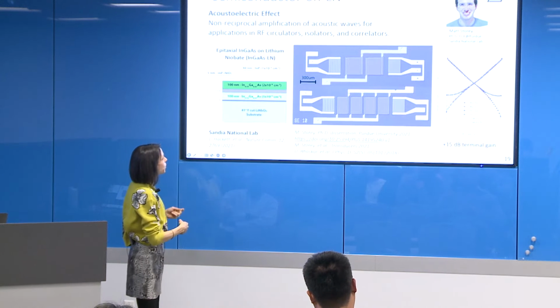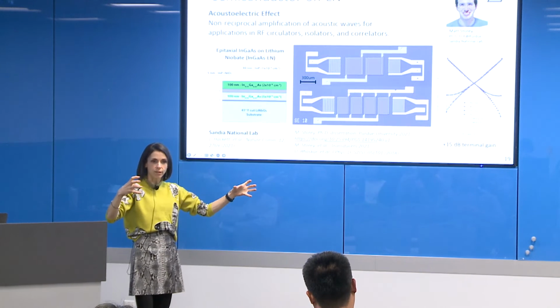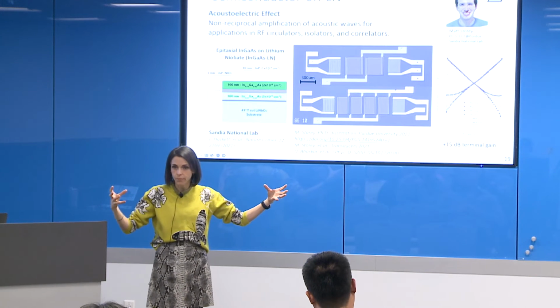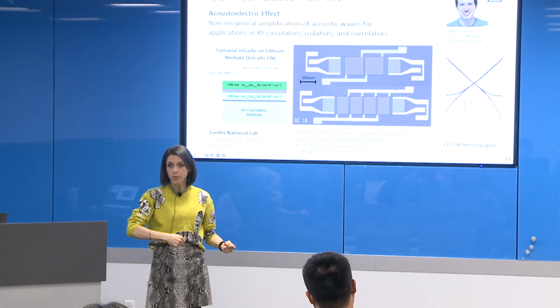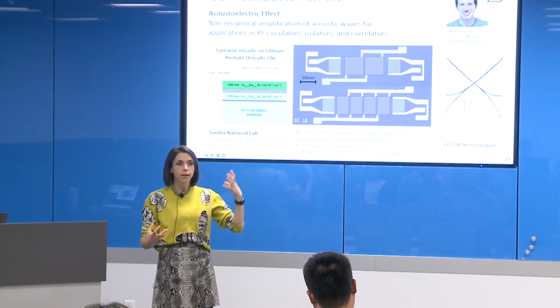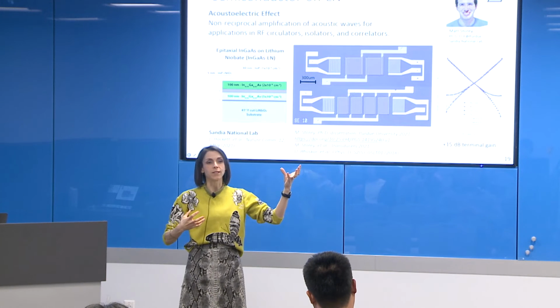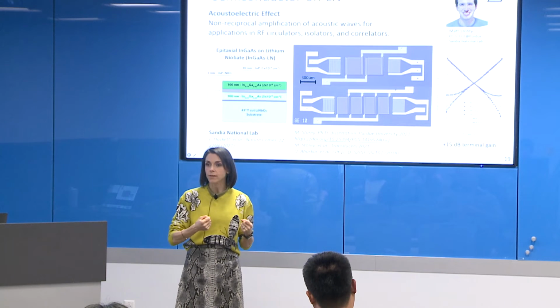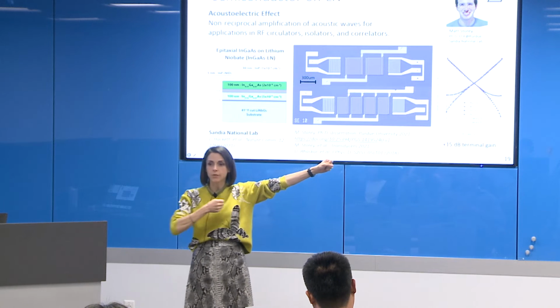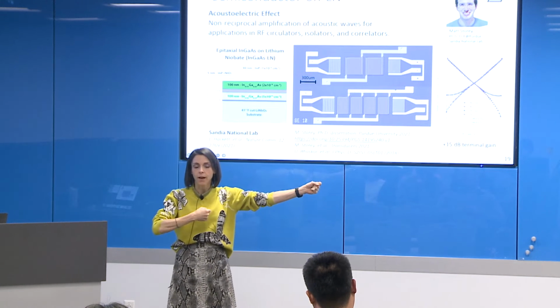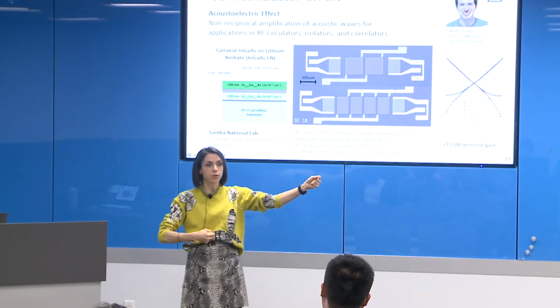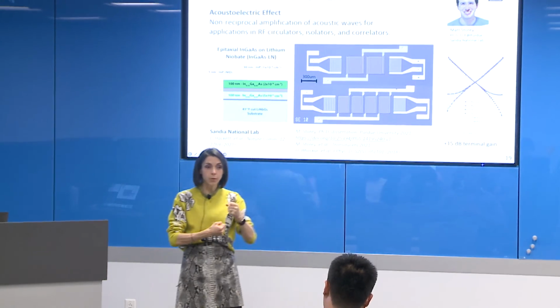That causes bunching of the free carriers up in the gallium arsenide heterostructure. You can make high electron mobility transistors in that. Those bunched electrons have their own electrical field distribution that then acts back on the wave, on the piezoelectric wave, and you have this exchange of energy between the acoustic wave and the free carriers. So with that, you could do a lot of interesting things. One, you can attenuate the wave depending on how fast the electrons are going relative to the wave. One drags the other. Either you can pump energy from the electrons into the wave, amplifying the wave, or you can attenuate the wave by reducing the velocity of the electrons. You can tune the velocity of the wave and therefore the frequency or the phase of the wave as it's propagating, and do a whole bunch of RF signal processing associated with all of that, amplifiers and so forth.